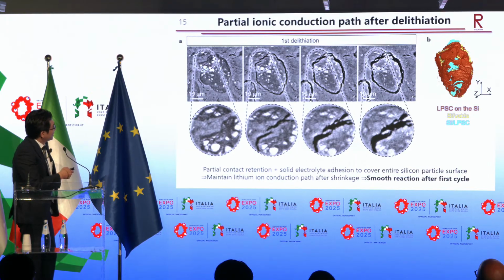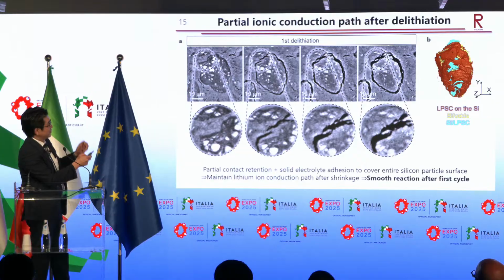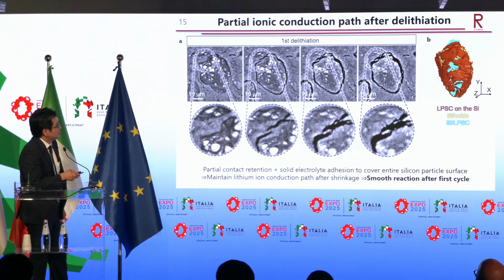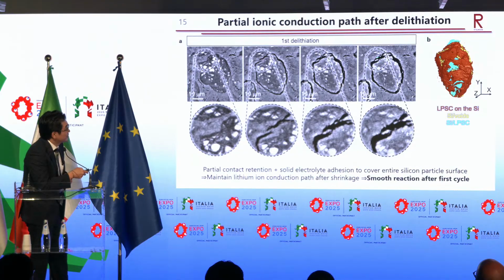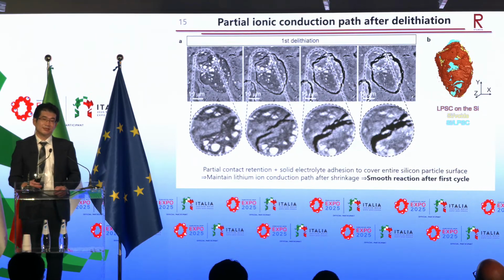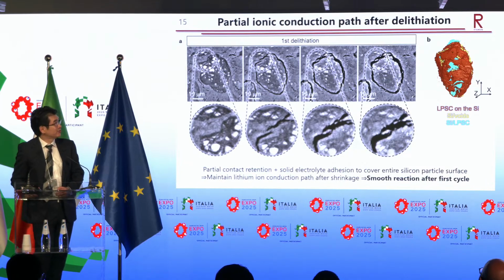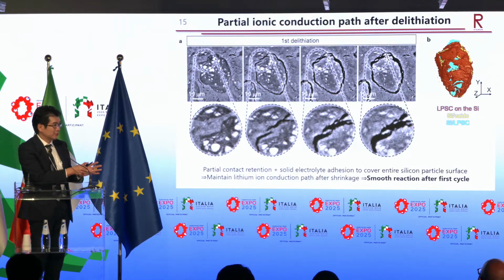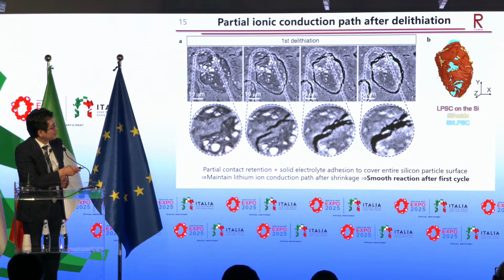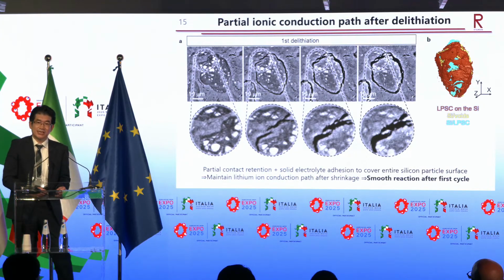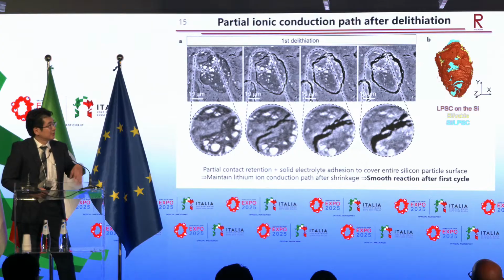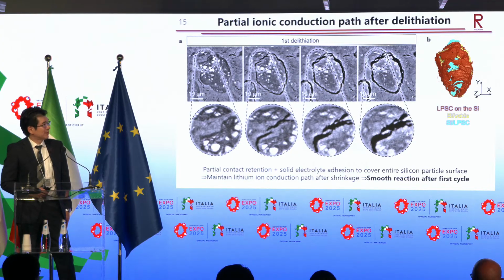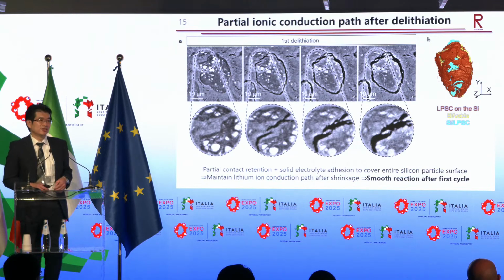So this is the silicon active material, and for the discharge reaction, silicon shrinks here, here, and here. So the contact state between silicon and electrolyte is lost. However, when looking here, partial contact using a bridge between the silicon active material and electrolyte is maintained, even though most of the contact is lost. So this is a discharge state, but using this small contacted bridging state, lithium ion can be supplied. So for the discharging reaction, lithium ion can be supplied and silicon is expanded, and the reaction can proceed.